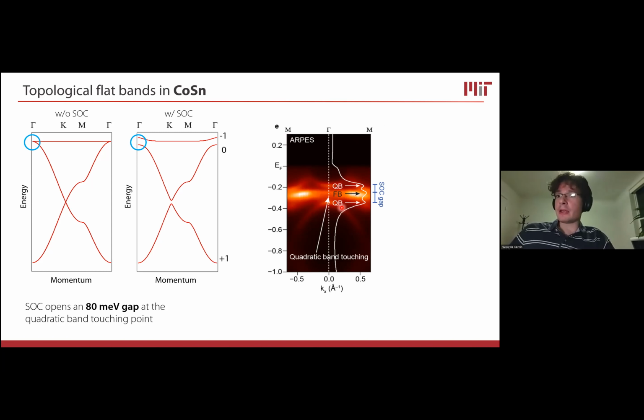But experimentally and theoretically from band structure modeling, we find that this gap exists and endows the flat band with topology. So it's not a finite Chern number like in the case of the previous material, which has time reversal symmetry broken. But we still have a non-zero Z2 index, which we can find from analyzing the parity eigenvalues for the time reversal symmetry preserving momenta. So the M points and the gamma point.